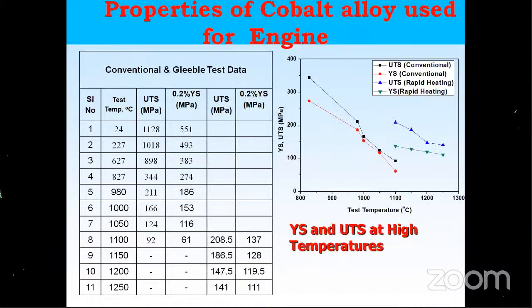Interestingly, I got very, very interesting results. At 1100 degrees, suppose I do a test the conventional way, I get only 92 MPa UTS and 61 YS. Elongation will be very, very high. And if I do the same thing with the actual flight conditions, the test pattern I showed is the actual flight condition, I'm getting 208 plus UTS and 137 YS. So even up to 1250 degrees centigrade, I'm getting a very high value. I could have gone more than that, but then the problem is it is never warranted. So that I didn't do.